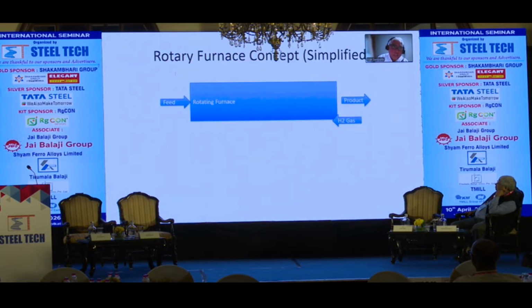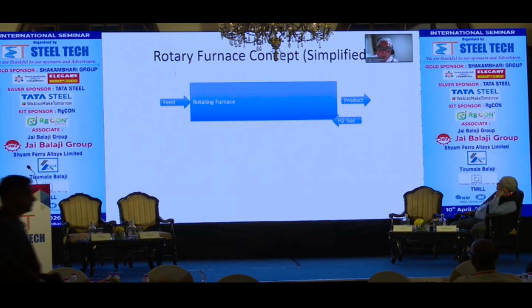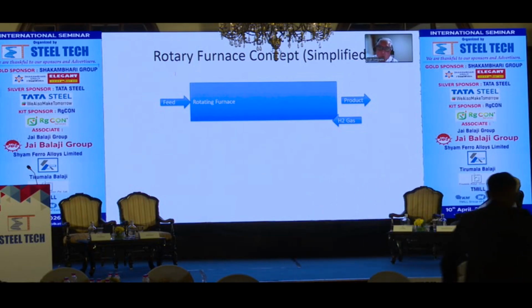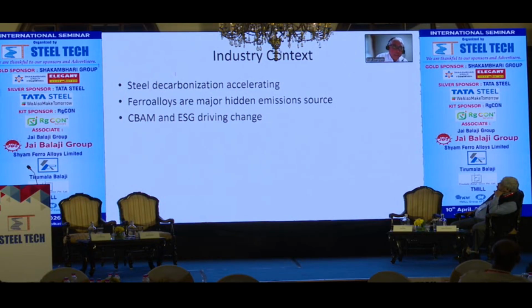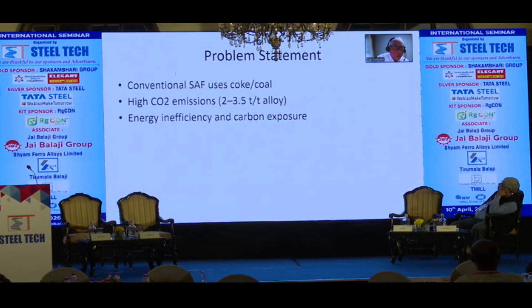What I'm suggesting is we have the feed, we put it into the rotating furnace in a counter-flow way. The hydrogen flows in the opposite direction, and we pre-reduce the ore before we feed it into the furnaces. The industrial context here is that steel decarbonization is accelerating. Ferroalloys are a major hidden emission source, and carbon border adjustments and ESG are driving the change. As we talked about, conventional SAF uses coke and coal and has high CO2 emissions, 2 to 3.5 tons per ton of alloy, and energy inefficiency and carbon exposure are the problems.